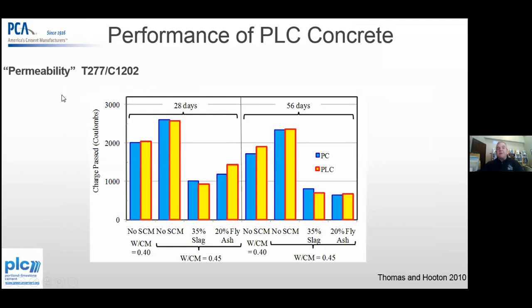Permeability, the C1202 or the T277. Without SCMs, you're going to get higher permeability numbers. Always do, because of the pore solution, your calcium hydroxide pore solution. That's known. But once you start adding pozzolans or supplementary cementing materials, you end up reducing your permeability to levels where you can meet specification requirements.